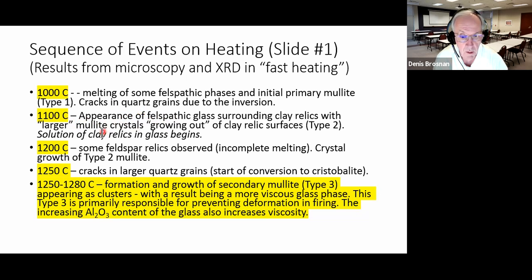A little bit higher, we can begin to develop not only mullite on the relics of clay crystals, but mullite growing out from the clay crystals. Eventually, about 1250 degrees C, we can begin forming secondary mullite. That's mullite crystals that grow to very long sizes, long fiber sizes. Their aspect ratio changes, and these crystals really impart viscosity to the glass phase. Now, some of the alumina from the metakaolin is dissolving in the glass.